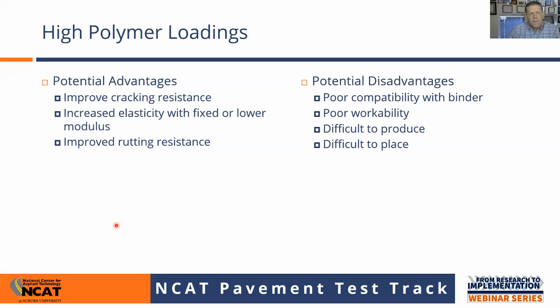So when we think about loading up polymer into binders and into mixes, there's certainly some advantages of why we would want to do this. First and foremost is the potential to improve cracking resistance by having that polymer in there. It'll toughen up the mix and make it potentially more crack resistant. We can increase the elasticity with a fixed or lower modulus, and maybe also improve the rutting resistance. So those are some pretty good advantages. In fact, some of the reasons why we use conventional polymer loading, around say 1 to 3% or in that ballpark, is that we get those sort of advantages.